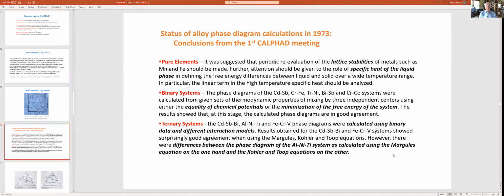Well, the conclusions that we came to at the end of the first meeting, with regard to the pure elements: it was suggested that periodic reevaluation of the lattice stabilities of metals such as manganese and iron should be made. And manganese and iron were of particular interest, not only because of the importance in steels, but because, of course, with those two elements, the magnetic effects needed to be taken into account also. And that was the intention of the group in proceeding further. Further attention should be given to the role of specific heat of the liquid phase in defining the free energy differences between liquid and solid over a wide range of temperature. In particular, the linear term in the high temperature specific heat should be analyzed.